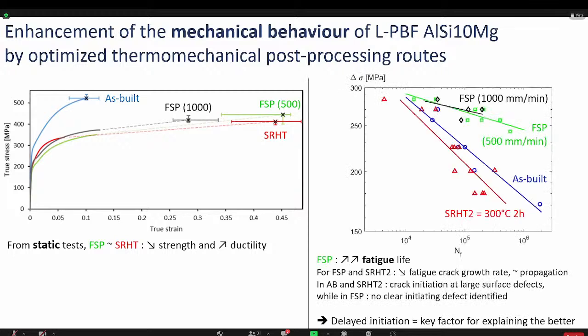Now if you look at the fatigue properties, again the FSP material is in green, the as-built in blue, and the stress relief in red. In that case, you can see that the FSP greatly improved the fatigue life of the material, especially if you compare it to the as-built or even to the stress relief material. And if you look at, for example, fatigue crack growth propagation, both FSP and stress relief material have quite similar behavior in terms of propagation of the crack.